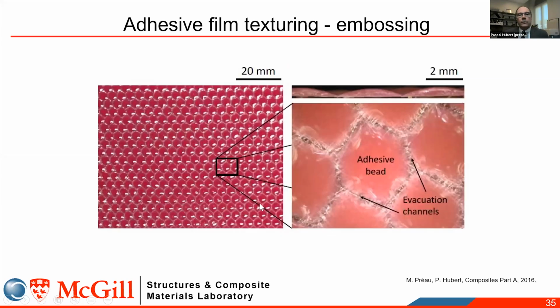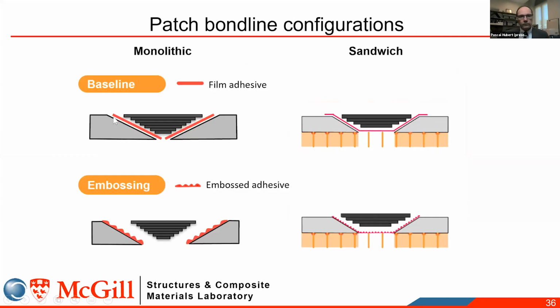One way of doing this is to do something to the adhesive. And the solution that we developed was to do an embossing of the adhesive. And by embossing, you create these little evacuation channels that will allow air to escape. To show you how it works, we can compare a repair done with a normal film adhesive and then an embossed adhesive. And you can see here the two configurations for monolithic and sandwich.